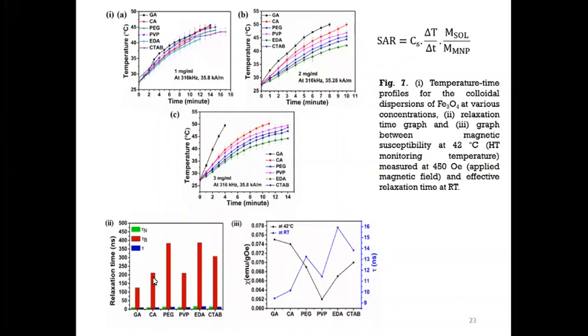So even if it looks similar, due to the different surface functionalization, the difference in size, and the arrangement of the atoms inside the materials, the relaxations differ. This is the effective relaxation, this is the Brownian, and this is the tau N, the Néel relaxation. So these relaxation mechanisms are different, as well as the susceptibility. So we have to measure the susceptibility at the hyperthermic temperature also. We can see that there is variation in the susceptibility, as well as variation in the effective relaxation of the materials.